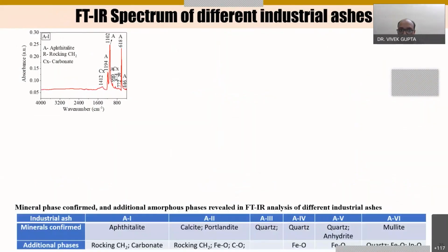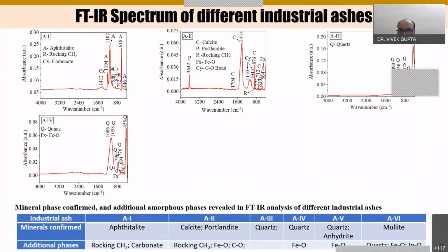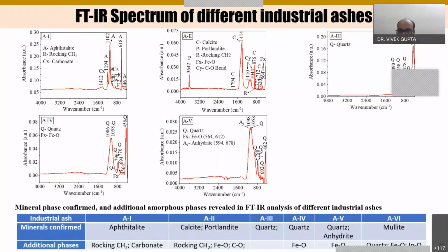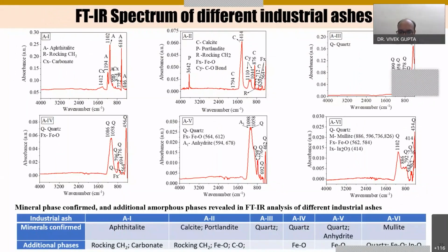So these are the different FTIR spectra where we found different amorphous phases which are not identifiable in the XRD patterns. You will see the A1 and A2. We have observed the rocking CH2 bonds. Here we can say that the high LOI values of A1 and A2 are because of the CH2 bonds present in the ashes, and you can notice that in the A1 we have observed the presence of carbonate also. So that actually enhances the high LOI value of that particular A1 ash.